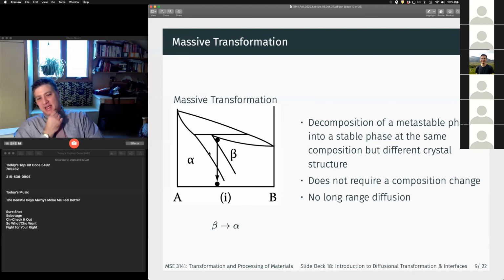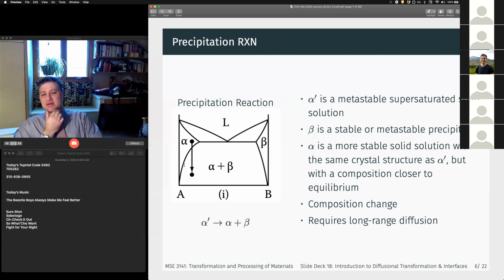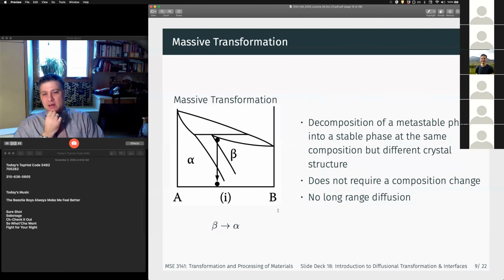So you can imagine that the kinetics of something like this is going to be much faster than a precipitation reaction, right? Whereas this precipitation reaction is going to be dependent on how fast we can move B through our system. A massive transformation is only going to be dependent on how fast we can do some local atomic jumps, right? And if we think about the time dependence of diffusion, right, that square root dt term that comes into our diffusion length is really the killer, right?